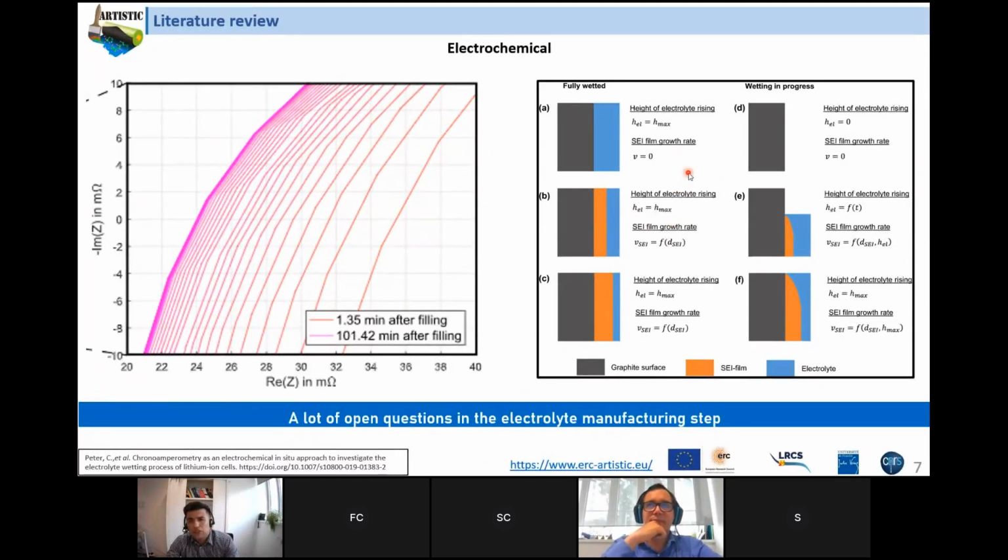I found out that they try to combine measurement of the electrolyte infiltration degree with the first cycling step. So when you have a lot of electrolyte, after wetting, you apply current and you measure the potential. So SEI formation takes part, right? But then what they're doing is applying current, measuring potential, but with different degrees of electrolyte, there is a different form of SEI growth.